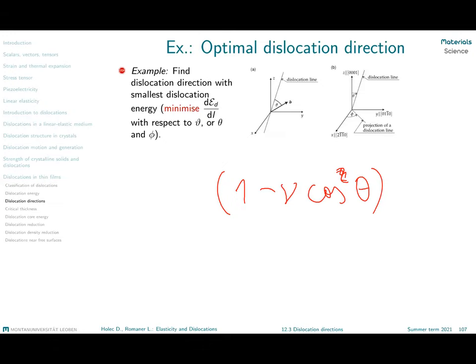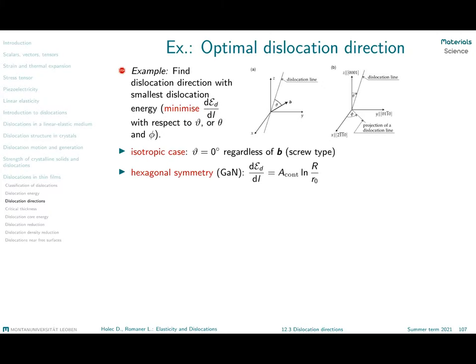What happens when we do not have elastically isotropic material? We can investigate this because we now have the tools. We look at the dependence of the pre-logarithmic factor A_cont — where 'cont' means we do everything in the continuum approximation using the elasticity of the continuum — evaluated as a function of two angles, phi and theta, which define the orientation of the dislocation line direction for a given Burgers vector. I'll be showing an example for gallium nitride, which has hexagonal symmetry.